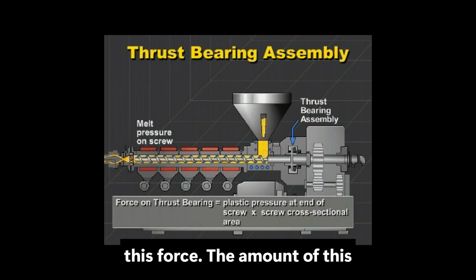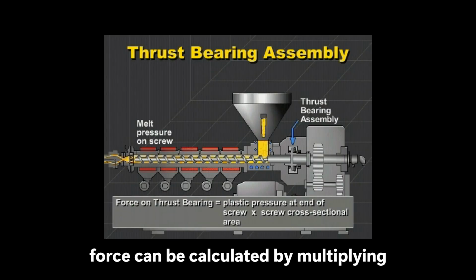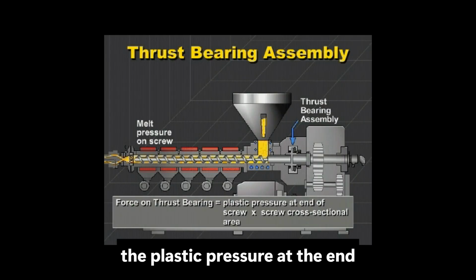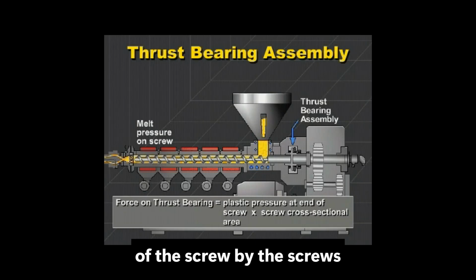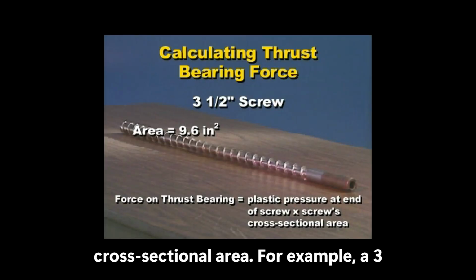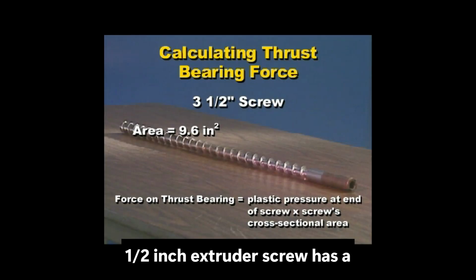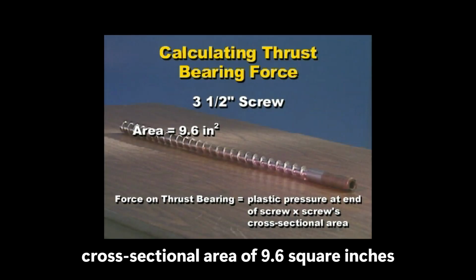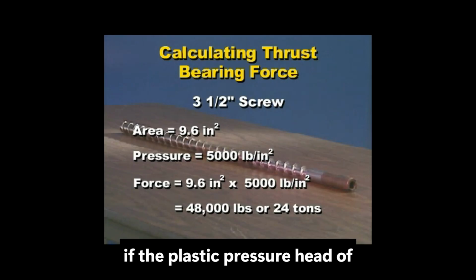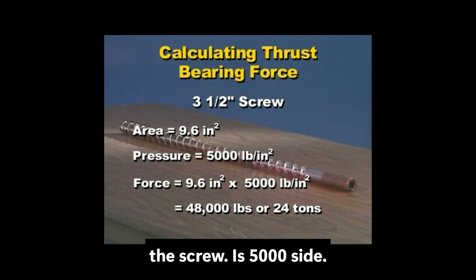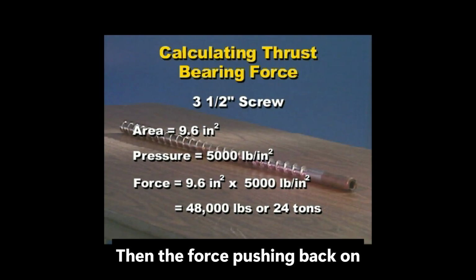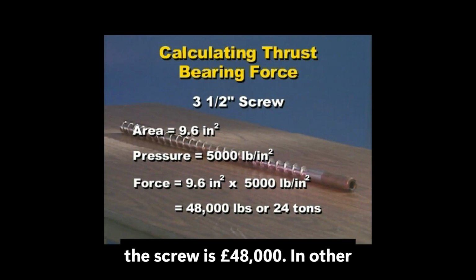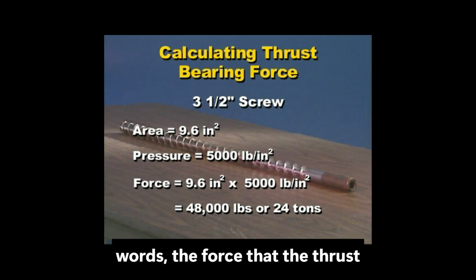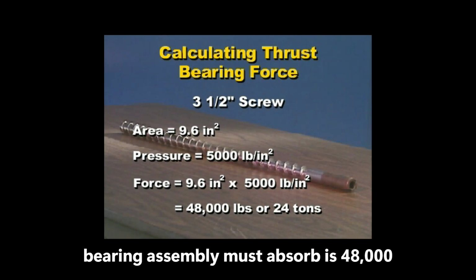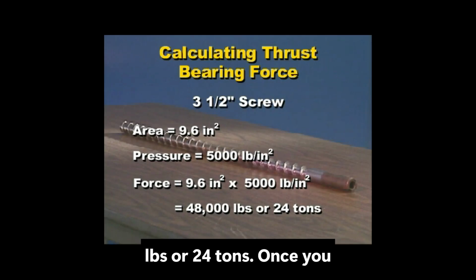The amount of this force can be calculated by multiplying the plastic pressure at the end of the screw by the screw's cross-sectional area. For example, a 3.5-inch extruder screw has a cross-sectional area of 9.6 square inches. If the plastic pressure at the head of the screw is 5,000 psi, then the force pushing back on the screw is 48,000 pounds. In other words, the force that the thrust-bearing assembly must absorb is 48,000 pounds or 24 tons.